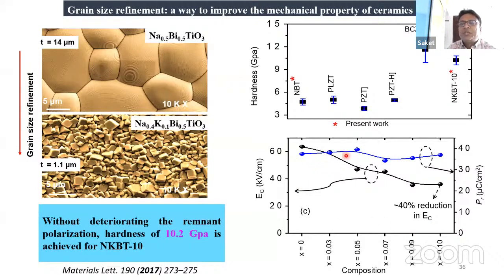And here you see the polarization value is almost constant, with a 40% reduction in EC. As I mentioned earlier, we have to reduce the coercivity while retaining the polarization. So without compromising the ferroelectric or piezoelectric character, as we can say from the PR, we increase the hardness. How? Just by grain size refinement. It is a traditional technique.